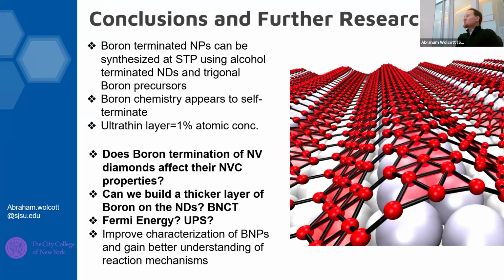Okay, so as we conclude the boron section, we can say boron terminated nanoparticles can be synthesized at standard temperature and pressure using alcohol terminated nanodiamonds and trigonal boron precursors. The boron chemistry appears to self-terminate in a similar way to atomic layer deposition. It's ultra thin. We've estimated that we have about 1% atomic concentration. And if we look on the right-hand side, it's a picture like this that we can begin to glean from our data set.